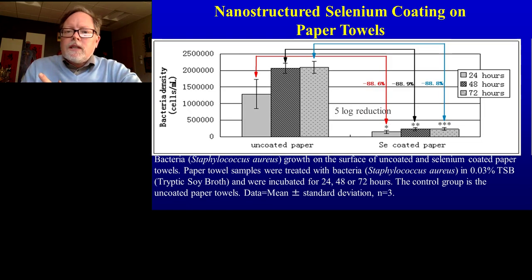So when doing so, we're seeing great decrease in bacteria attachment, decrease in bacteria growth. Here's just some of the raw data for, again, Staphylococcus aureus, but we've seen this for many bacteria, where you see a significantly reduced 5 log reduction in bacteria growth after 24 hours, 48 hours, 72 hours when coating these paper towels with selenium.